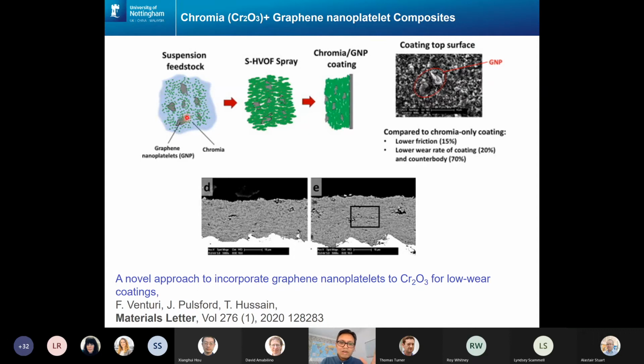So what we're doing is we're developing chromium oxide with graphene nanoplatelet, and then we spray them using suspension HVOF, and that's how we get the GNPs built into that chromia. And what it does, it can lower friction by around 15% in that system, and wear rate on the coating by 20%, and on the counterbody, in this particular case alumina, around 70%. So by making simple composites based on ceramic, the performance can be enhanced significantly. So these are some of the microstructures, scanning electron images, showing you the robustness and the uniformity of these coatings.